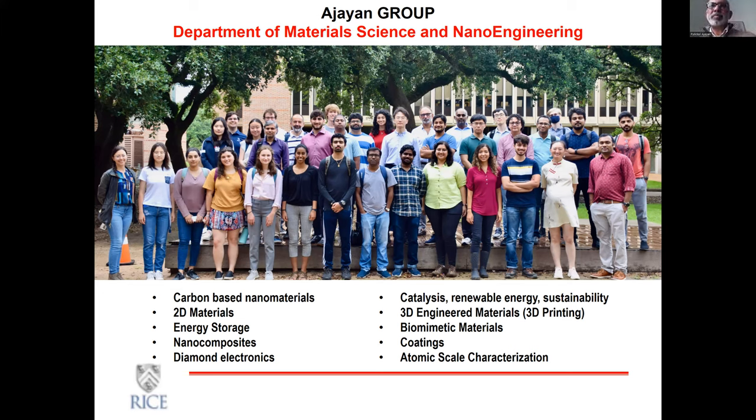Yeah. I mean, there have been multiple approaches to make these graphene flakes or quantum dots reactive. One of them, of course, is to use the edges. And as you said, if the edges are not really terminated with specific things like hydrogen, it should be quite reactive because you have a dangling bond right there. There is another aspect which we have been pursuing and many others as well, which is to substitutionally dope graphene with nitrogen, phosphorus. There are many elements that you can insert, which creates a different type of defects.